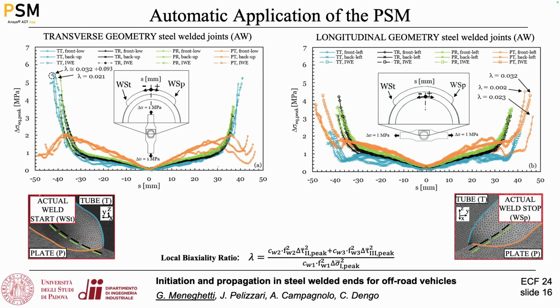You see here all the stress fields along the weld toe and weld roots, both with the idealized and the real geometry. If we start from the transverse geometry, you can see that the maximum equivalent peak stress with the reference load is here. This symbol is the weld toe at the tube side. In this case, we have the maximum stress for the longitudinal geometry at the weld toe in the plate side. So weld toe plate side is here, weld toe tube side is here.